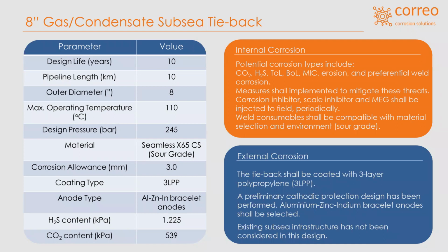For the external corrosion, we decided to select a 3-layer polypropylene anti-corrosion coating. This was due to the maximum operating temperature being 110, which was in the range for 3-layer polypropylene, but not other coating systems such as FBE. We also have performed a preliminary cathodic protection design, and aluminium zinc indium bracelet anodes shall be welded to anode pads along the length of the pipeline at approximately 300-meter increments.